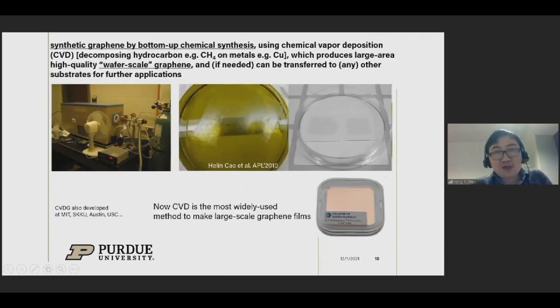It worked very well. These are some examples of very large size graphene grown on copper. Then you can further transfer by etching copper off to almost any substrate. You can call these wafer scale graphene. Of course, industry these days can even grow much, much larger size with a much bigger furnace. And today, this is perhaps the most widely used method to make large scale graphene film. You can in fact buy them from companies, and so on and so forth.